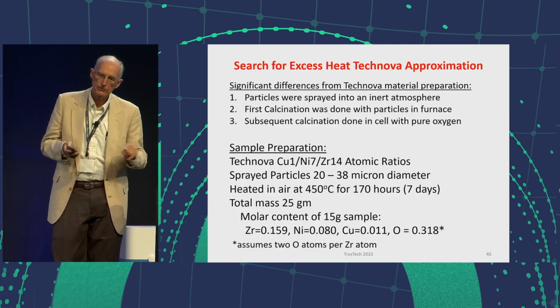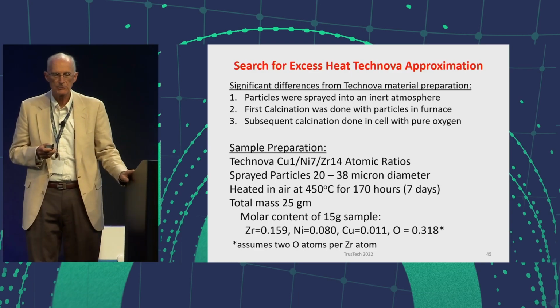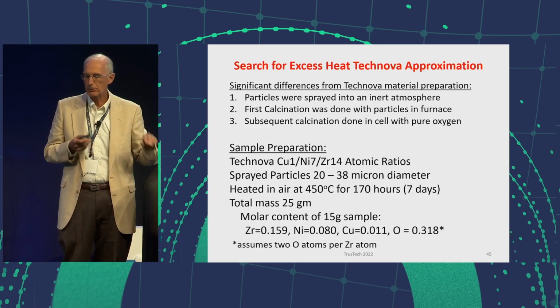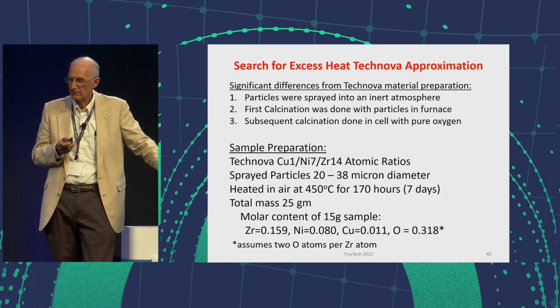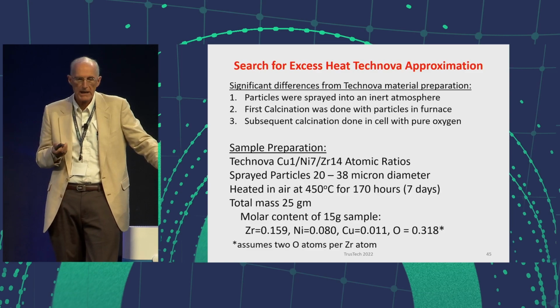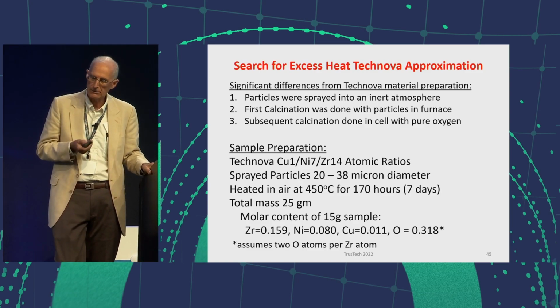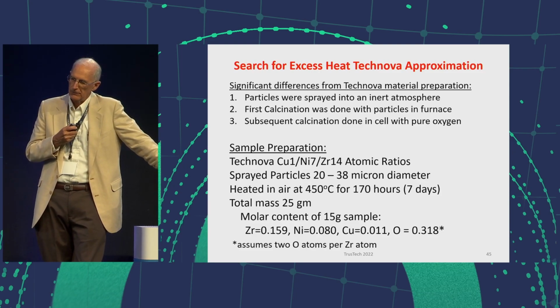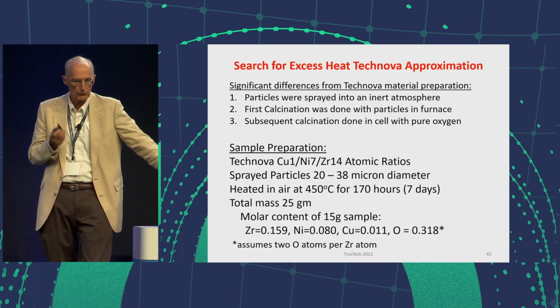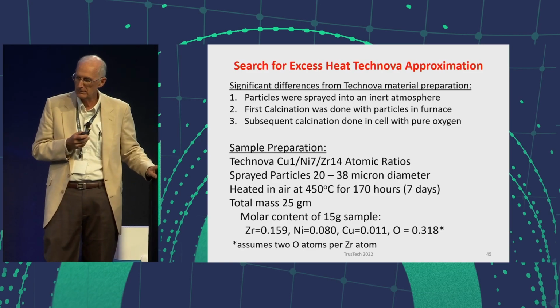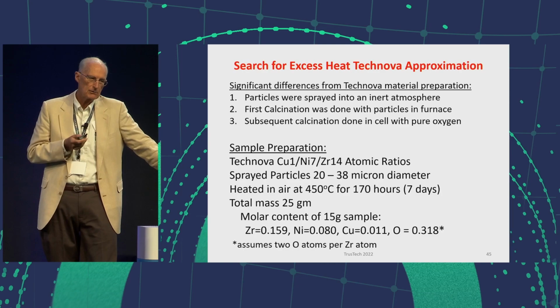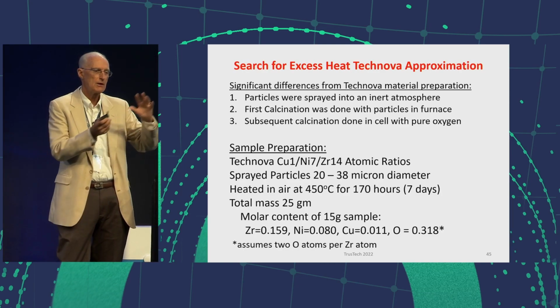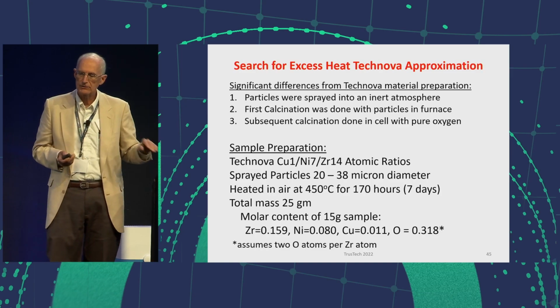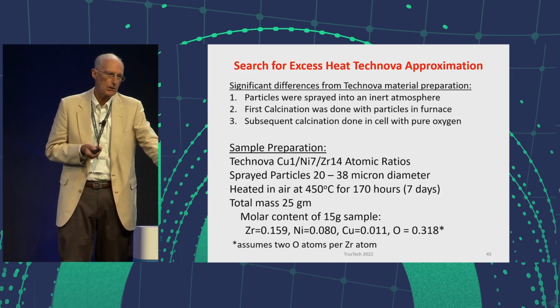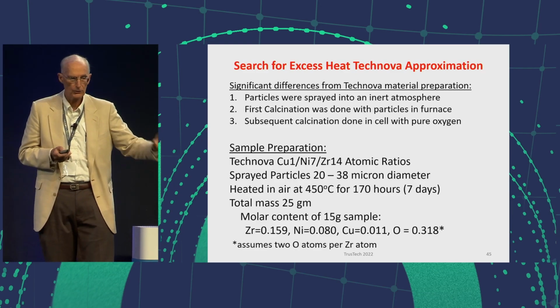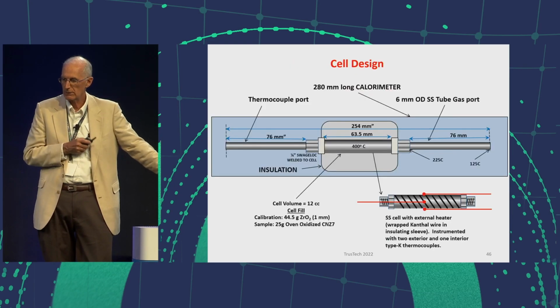So what I want to emphasize is this is not a replication study, because I changed completely the preparation of the material. Significantly, the particles were sprayed, and they were not taken from spun ribbon, which is, I think, the correct way to do, as you'll see in a minute. The first calcination was not done of ribbon, but was done of these particles, which are thicker than the ribbon, and that's significant. And in subsequent calcinations, they took all the material out and reheated it in the furnace. I decided to see if I could try to do it in the cell using pure oxygen instead of air. So those are significant differences, and that's why I do not consider this a replication study.